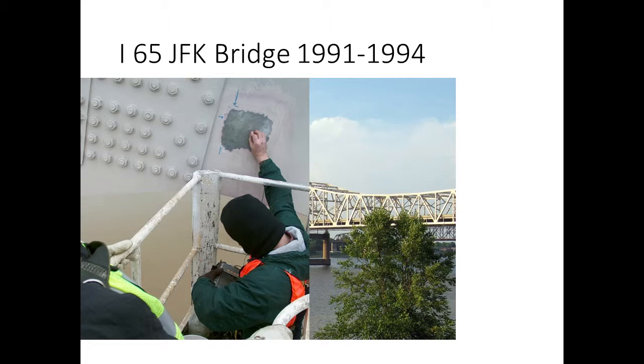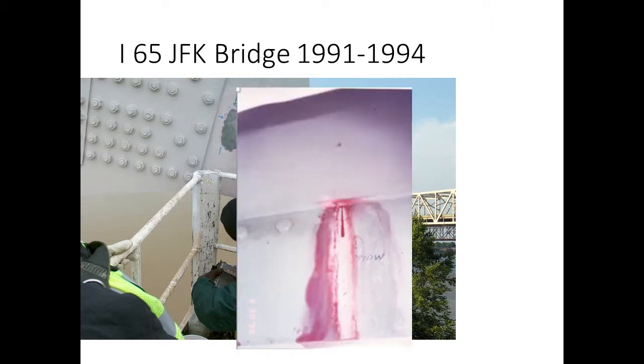It has several fracture critical elements, including this upper chord here that's made of the high-strength welded T1 steel. And they had detected cracks on the bridge. And somewhere starting about 1990, 1991, there was some non-destructive testing that was performed. And in this particular example, this is upper chord. They found a large crack.